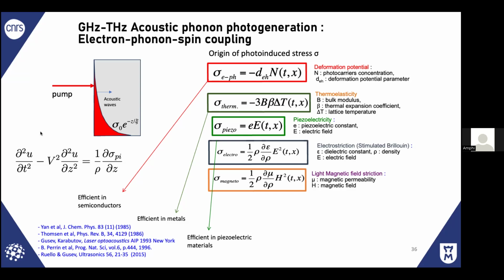But in that case, if you are below band gap, it's not written like that here, but these two quantities are tensorial. So for electrostriction, which is also Brillouin, it is important. If you turn the polarization, depending on the symmetry, the electrostriction tensor is for sure dependent on the light polarization. So mainly the light polarization is important with below band gap excitation when it is not resonant. If you have above band gap excitation, it's usually less important from the acoustic point of view. Of course, if you excite optical phonon with the Raman tensor, in that case it has some importance for the light polarization.